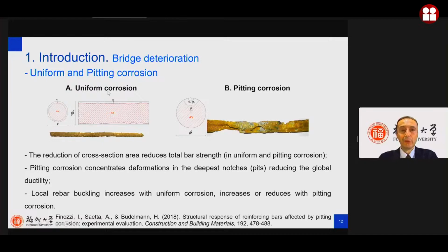The corrosion, and also this one is really well known, can be due to the uniform corrosion, so the cross section is going to uniformly change, but there can be also the so-called localized corrosion or pitting corrosion. So there is a reduction of the cross section area, and so if there is a reduction of the cross section, of course there is a reduction of the rebar strength, but also the concentration of the deformation in the deepest notches that are called pits, so it's due to the pitting corrosion, reduce the global ductility.